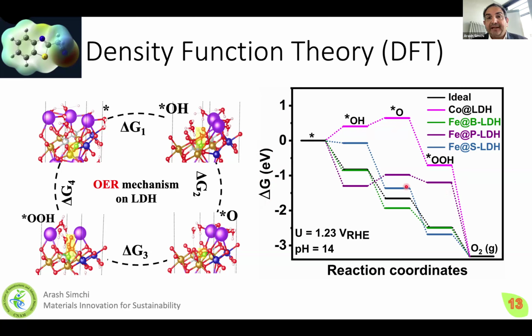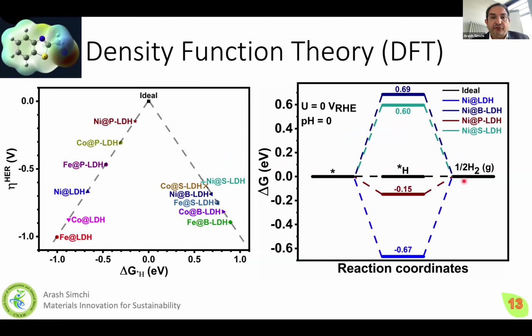As you see here, the energy of the system for this reaction changes significantly. It helps us to have a better understanding of the mechanism of action. We did the same for the hydrogen reaction, as you see here in the right figure. The energy of the conversion and dissociation of water to hydrogen gas depends on the type of nickel, for example, phosphorus, boron, and so on. And we can make such a diagram, putting all the different materials in eta, the overpotential for the hydrogen evolution reaction, and delta G is the energy for the reaction of the hydrogen conversion.